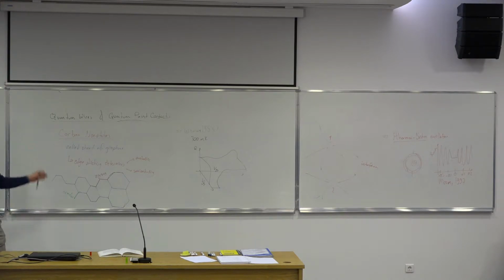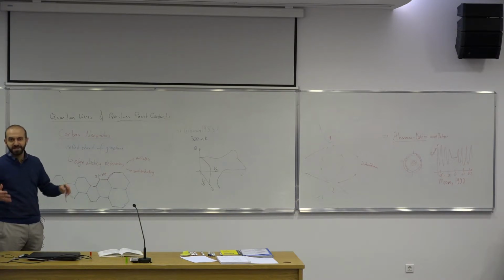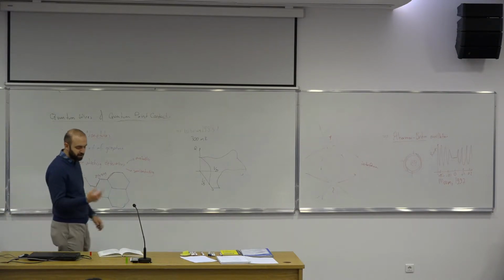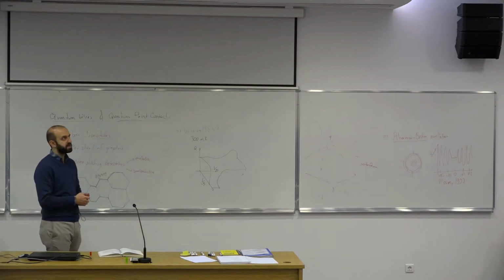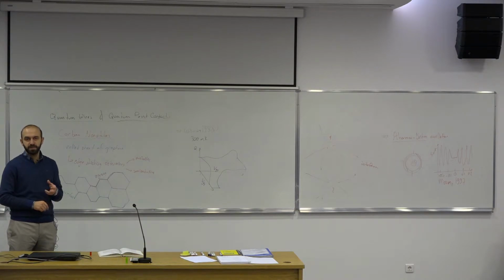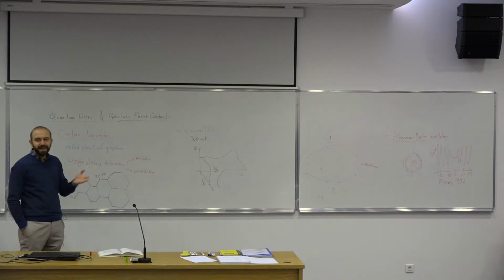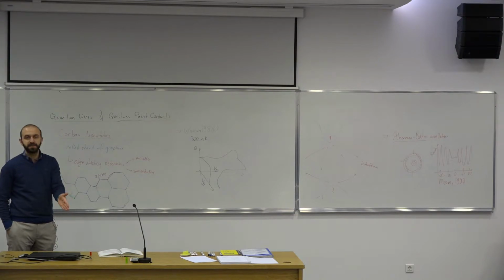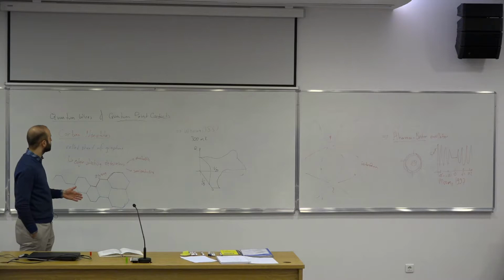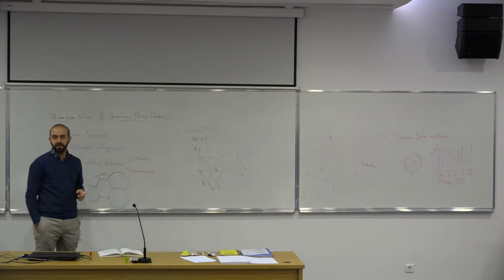When I was doing my PhD, my group was also working on carbon nanotubes, and we had a furnace dedicated for carbon nanotube synthesis, but it was like black magic, you know? You just send gases in, then you have this precursor. It was some iron oxide compound, and they would send hydrogen and methane into the furnace at about 900 degrees Celsius. Then they ended up with carbon nanotubes, and they didn't know really how. I think they know the mechanics, but they always got single-walled carbon nanotubes, and from time to time they could get metallic or semiconducting ones.